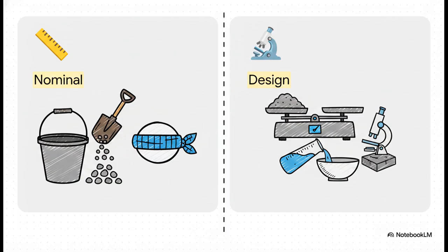First off, we use precise weight batching, not volume. Secondly, the ratios are not fixed. They fluctuate based on the specific local materials you're using and are meticulously engineered using the IS 10262 2019 codebook. Plus, we don't just stick to the basic 4 ingredients. We bring in chemical additives, like plasticizers to cut down on water while keeping the flow smooth. Or we add fly ash and GGBS to completely alter the concrete's core properties.